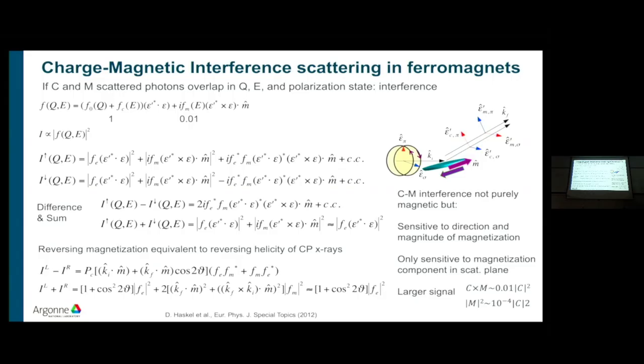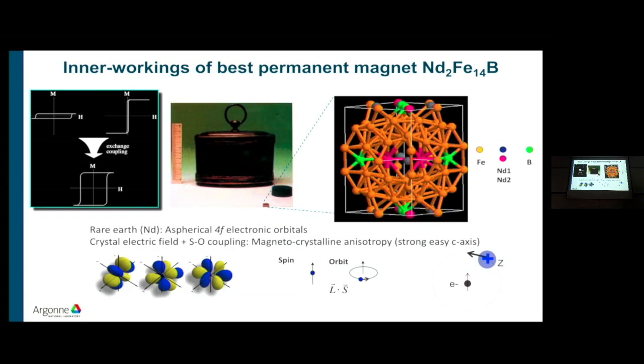But the main point here is the charge magnetic interference is not purely magnetic, but sensitive to the direction and the magnitude of the magnetization, only to the component in the scattering plane. And now I have a 1% signal instead of 1 part in 10,000. So I want to show you one example about permanent magnets where we use this charge magnetic interference.